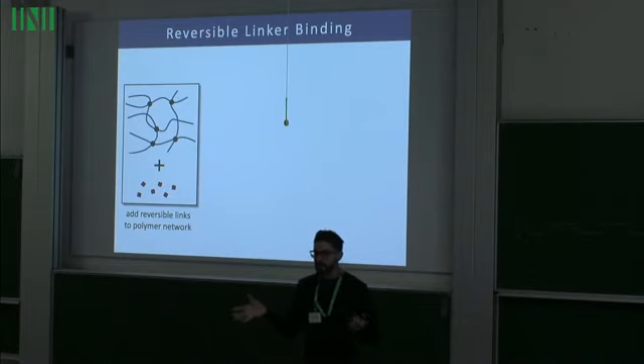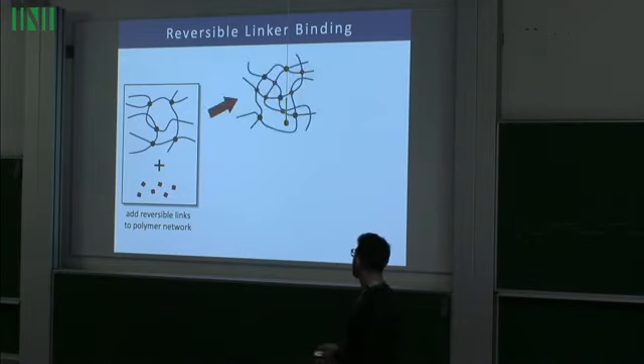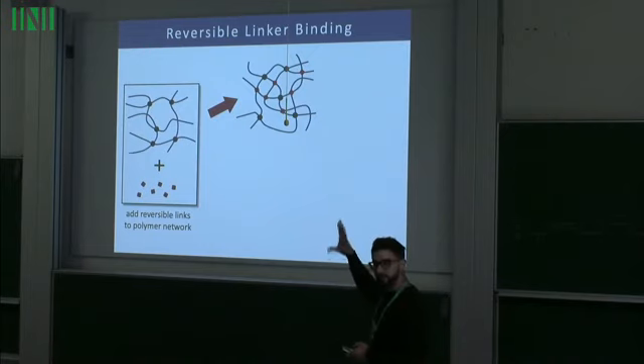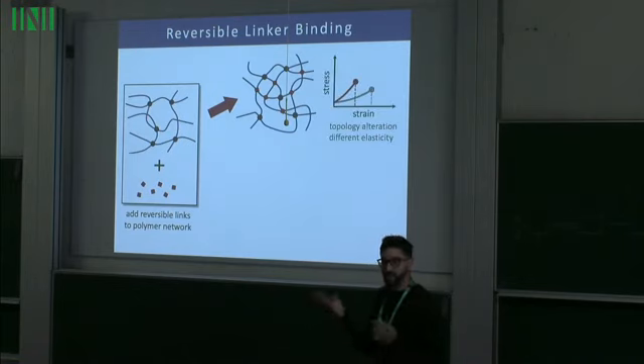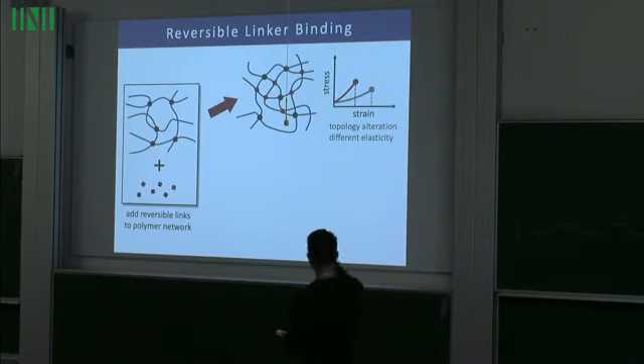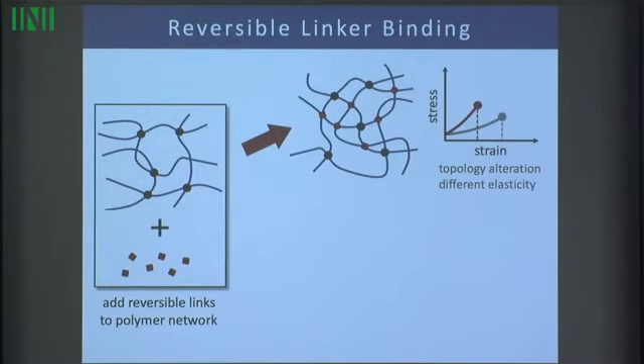And so if we now think about taking a permanent network and we want to add reversible crosslinks, but we don't want to change the force response, we can't really do this, because if I just randomly distribute the reversible crosslinks across the network topology, then that will actually change the topology and it'll make it stiffer. Okay? And so we would expect that this is probably not what's happening. And so this might be the naive sort of entropically enthusiastic approach where the things are randomized.